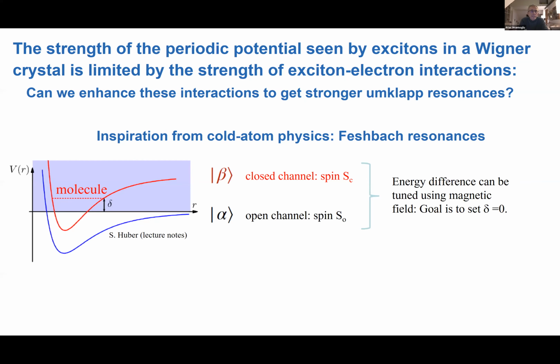What we did is that we got inspiration from cold atom physics, where the interaction strength between two particles, two atoms in their case, is controlled by the so-called Feshbach resonances. The idea is that, in addition to the scattering channel that you're interested in, which we will call the open channel, there is a closed channel, say distinguished by the different total spin of the particles. If this closed channel supports a molecular state, and if this molecular state energy can be tuned with respect to the open channel, so there are many ifs here, but this works beautifully well. If you bring this molecular state into resonance with the zero energy open channel state, then you can dramatically enhance the scattering phase shifts and go to the so-called unitarity limit.